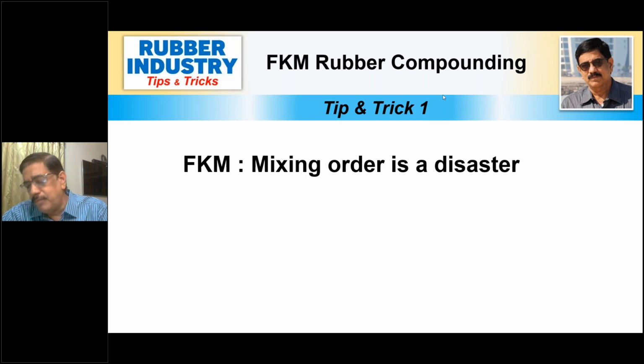So you will encounter severe problem if you add all the fillers first and then, thinking that accelerators, calcium hydroxide, magnesium oxide being accelerators, will add last. We will end up in the mixing with rubber, and there are a lot of patches of magnesium oxide sticking on the roll, and the magnesium oxide also will not get dispersed in the rubber.